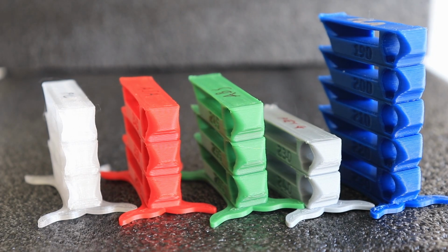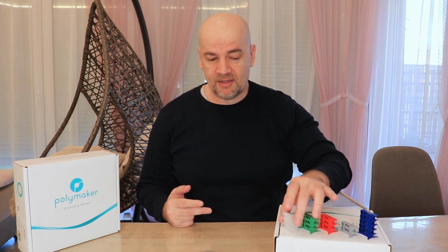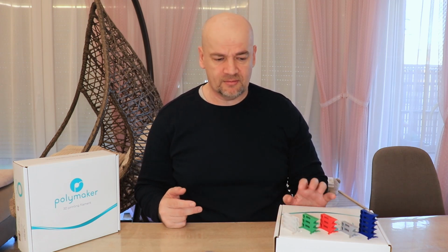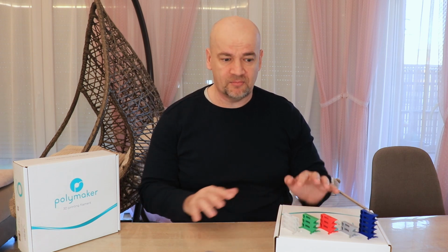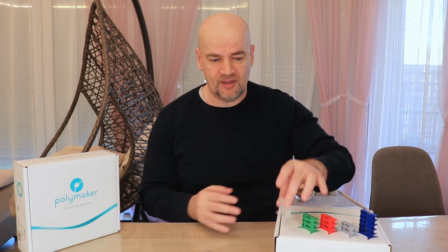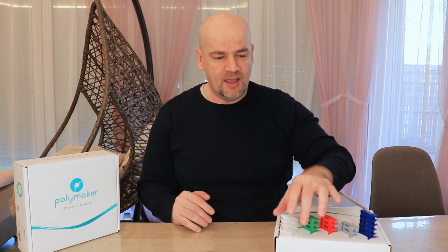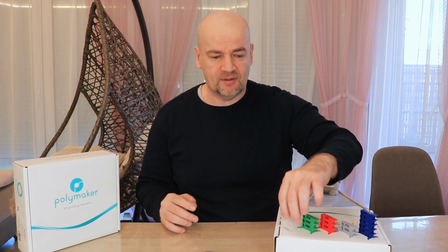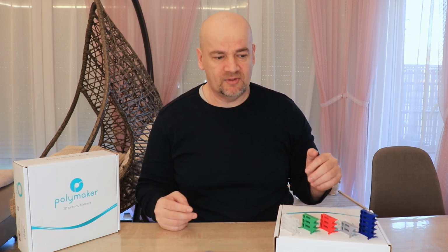So if you want to print inside an enclosure, definitely polycarbonate is a great material. For two reasons it is not my favorite. One is that I noticed later that it gets some warping. It is the hardest to print of these three. Definitely using a brim would help in this case, but I didn't use it. And the second reason is that it is very brittle. So if you expect your 3D printed part to get some impact, polycarbonate may break very suddenly, so that's why I don't recommend it for, let's say, plastic parts on a DIY 3D printer.